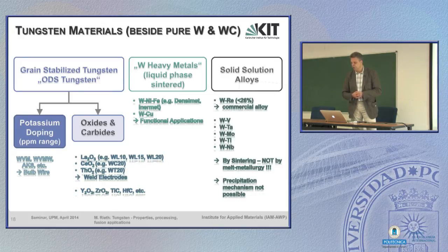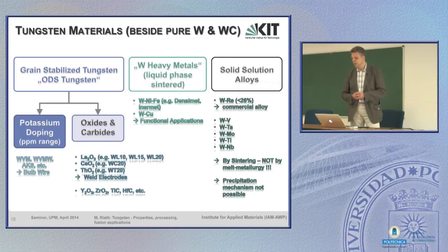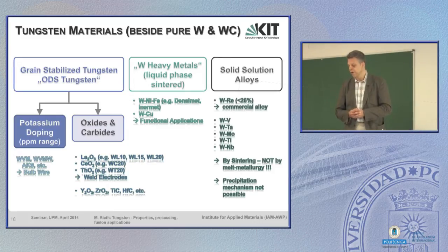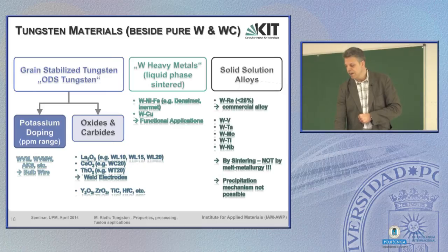and easy production method. They are sintered in a liquid phase, which means the second phase, which is either nickel iron alloy or simply copper, is melted with the tungsten particles inside, and this results in a dense and weighty material. Solid solution alloys are not frequently used. There is only one commercial alloy, that's tungsten rhenium, with a maximum content of 28% of rhenium. Many other alloys are thinkable. I will come to these